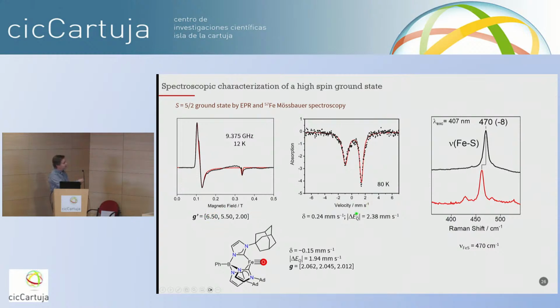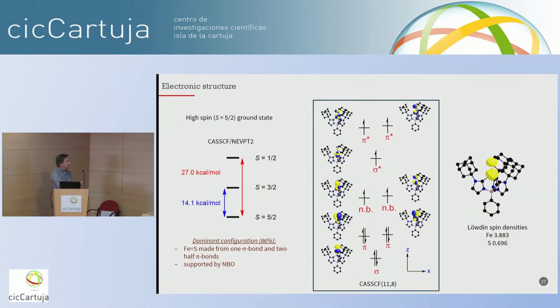If you look at the Mossbauer spectrum, the isomer shift is quite different from the oxo. Remember that one was negative. This is now positive. We could also get the iron-sulfur stretch by using sulfur-34, and we could assign the stretching frequency of 470 wavenumbers. And just again to compare with the oxo, the isomer shift there is quite negative in comparison to the sulfide. So we did quite a bit of computation to try and understand why this is a stable molecule.